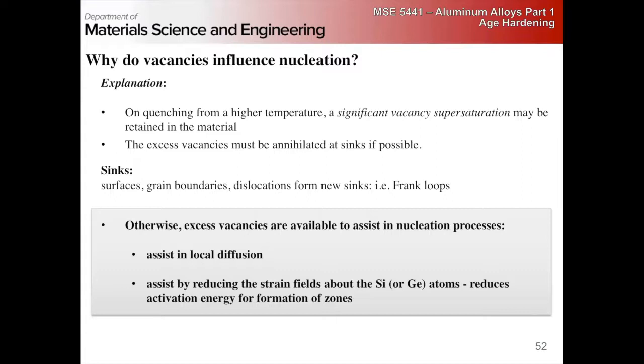If we have a hole in our lattice, a missing atom, we can't just magically populate an atom there. That vacancy needs to diffuse to a grain boundary or a surface, or an edge dislocation, or Frank loop. It can't just disappear. So there's a time dependence here.